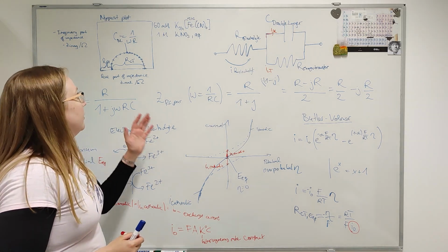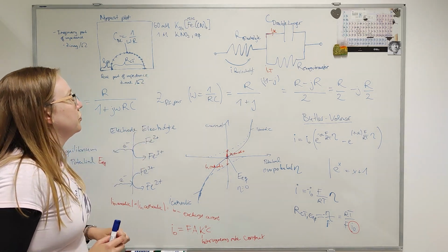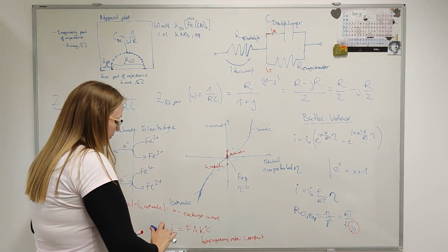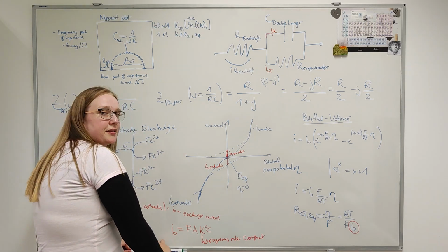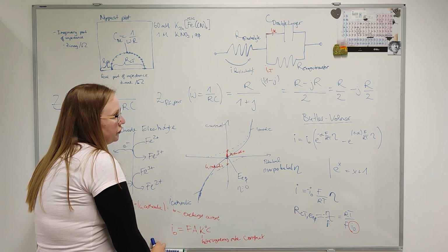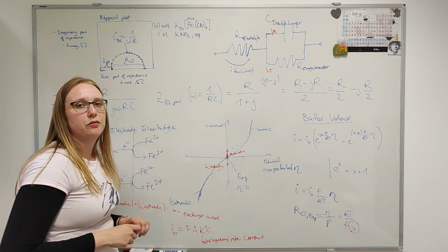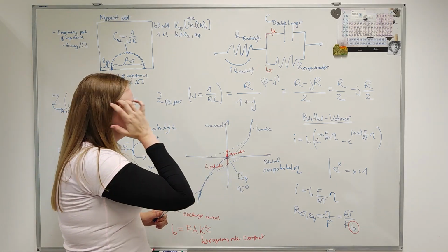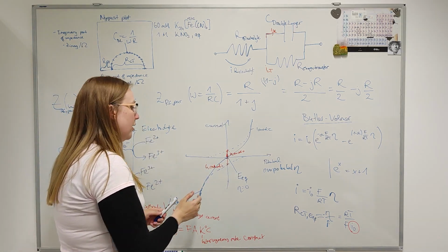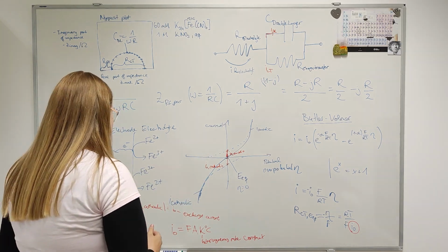What is quite remarkable about this example we have chosen with the iron 2 iron 3 redox pair is that it actually is electrochemically reversible. That means in the scan rate ranges we would use to conduct the cyclic voltammetry, you have also seen in Nastia's experiment, we would not be able to observe this current potential relation because we have a very fast kinetics.